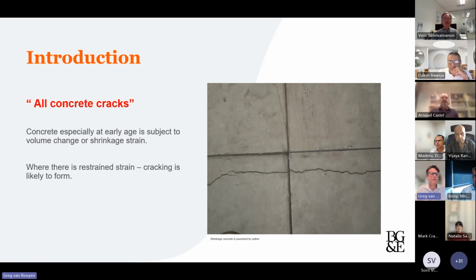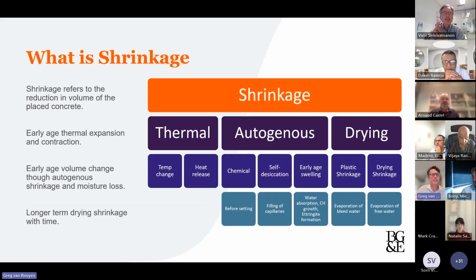So I guess we all know concrete cracks and the old saying, all concrete cracks. But concrete's actually really subject to volume change and strain, and cracking comes about because the strain is restrained and held in place. So I suppose what shrinkage is, it's the volume change in concrete. There's quite a few mechanisms, and I guess the work today, we're not really focused on thermal contraction and shrinkage. We're really talking about some early age and drying shrinkage. We typically talk about early age or plastic shrinkage in the first 24 hours or maybe a little bit more, depending on whose work you're looking at, and then drying shrinkage being the longer term reduction in volume through loss of free water in the concrete mix.